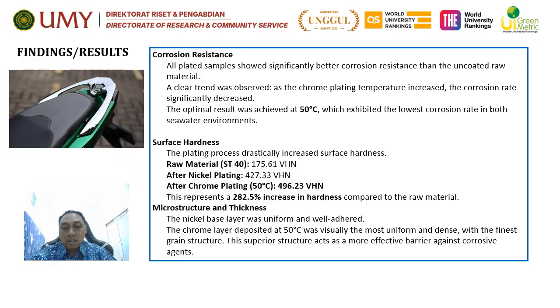And then the surface hardness: the plating process drastically increased surface hardness from 175 Vickers hardness numbers to 496 Vickers hardness numbers, and this represents a 282% increase in hardness compared to the raw material. And then the microstructure and the thickness: the nickel base layer was uniform and well adhered. The chrome layer deposited at 50 degrees Celsius was visually the most uniform and dense with the finest grain structure.